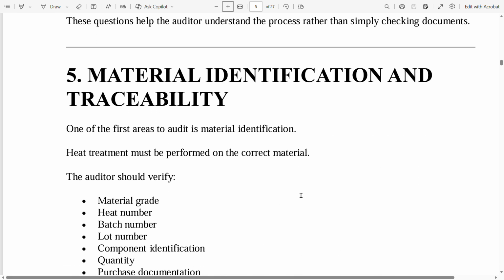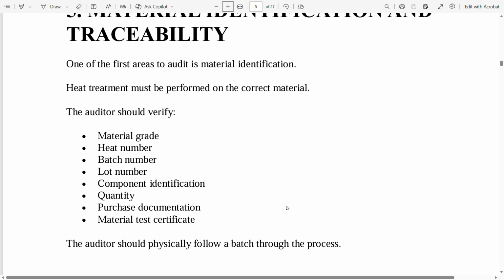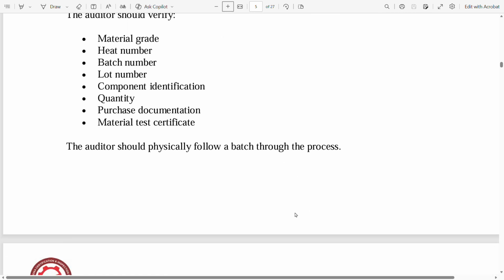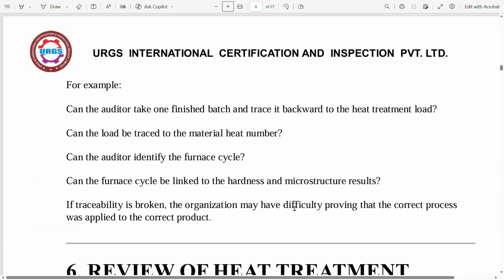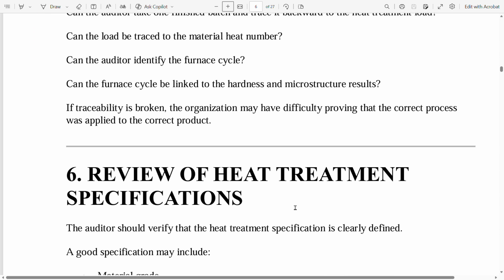Next is material identification and traceability. One of the first areas to audit is material identification. Heat treatment must be performed on the correct material. The auditor should verify material grade, heat number, batch number, lot number, component identification, quantity, purchase documentation, material test certificate. The auditor should physically follow a batch through the process. For example, can the auditor take one finished batch and trace it backward to the heat treatment load? Can the load be traced to the material heat number? Can the auditor identify the furnace cycle? Can the furnace cycle be linked to the hardness and microstructure results? If traceability is broken, the organization may have difficulty proving that the correct process was applied to the correct product.